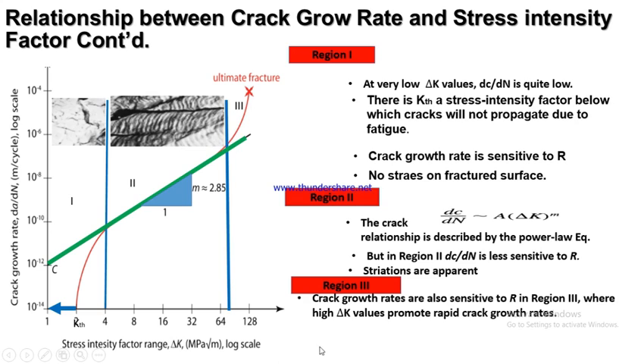Then in region 3, the crack growth rate is also sensitive to R, which is the stress ratio. You can see the profile begin to curve again, because we now have a curved profile, whereas here we have a linear profile in region 2. Another thing is that there is no striation at this particular part where the material fractures. At this part where the material fractures, you will not see striation. Striation will not occur in the material.